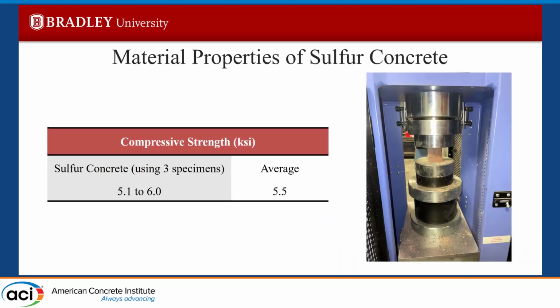In our next slide, we have just the material properties of plain sulfur concrete without any bamboo. So using 3 specimens, we tested our 2-inch by 2-inch by 2-inch cubes, and we're getting a range from 5.1 to 6 KSI for overall compressive strength, which is an average of 5.5 KSI, which is pretty large, considering that there are no additives in the sulfur concrete mix. It's just sulfur and the Martian soil, which, 5.5 is the low, which is pretty good.